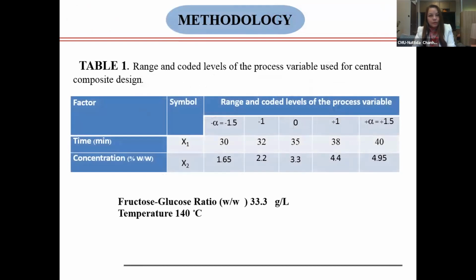The slide shows the methodology for the design of experiment, using central composite design. Table 1 shows the range and coded level of the process variables. It has two factors: time sample X1, ranging from 30 to 40 minutes, and concentration sample X2, 1.65 to 4.95 percent weight by weight, and a fructose glucose ratio of 33.3 grams per liter at a constant temperature of 140 degrees Celsius.